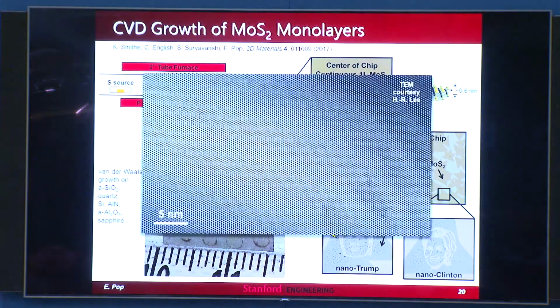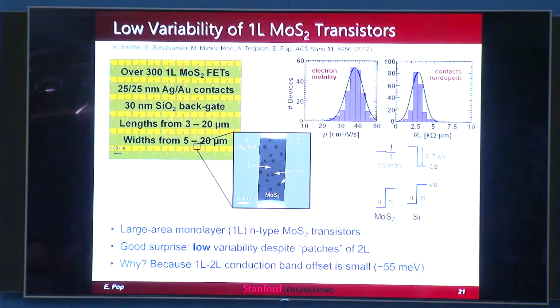And so we did, but before I tell you that story, I just want to show that at least where we have monolayers, they actually look pretty good. This is obviously a very small zoomed-in TEM image, but they do look like the way they should. You see the monolayer atoms, they're all there. Of course, if you look in other regions, you'll see defects and grain boundaries. But the stuff is there. It really does work.